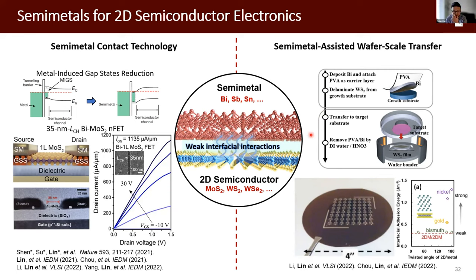From the material synthesis perspective, it is kind of both. In order to really make it into real production, silicon is at 12-inch scale processing right now. So we need to develop a synthesis approach that can offer high quality growth for 12-inch materials. At the same time, we need to make it perfect, ideally a single crystal material with as little defect density as possible. There has been very good progress in the past 2-3 years. You can see in publications that people are demonstrating larger wafer scale synthesis approaches. There are also different approaches to induce single crystal material growth. You can engineer the substrate.